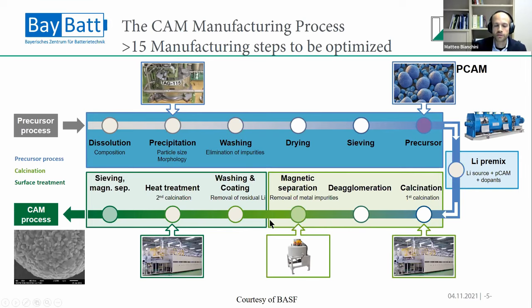And then there's a third major, now we made our lithium transition metal oxide. Now there's a third major part, which is still the final post-processing, the washing and coating, which is really needed to stabilize the material. And I will tell you more about this. So this is also a very important step. So as you can see, going from the initial sulfates to the finalized product, it can easily take many manufacturing processes, each of which needs to be optimized.